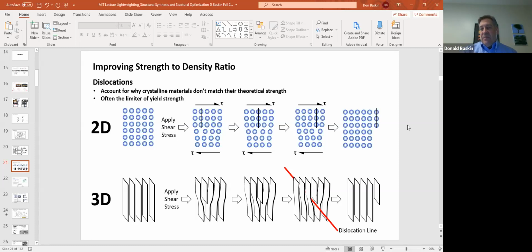Okay, when you take a piece of steel or aluminum or titanium or nickel or beryllium, and you pull it in tension, or push it in compression, those forces can be broken down into a stress based on the cross-sectional area, and it can be resolved into a shear stress. When a material deforms in shear, you're moving that dislocation down the lattice, and that's what creates the shear deformation in a metal. Like I show in the diagram at the top in 2D, as you shear this material, tau, you get this sliding of the dislocation, the missing column of atoms, down the lattice, and that leads over millions of grains to a far field shear deformation that you can really see.